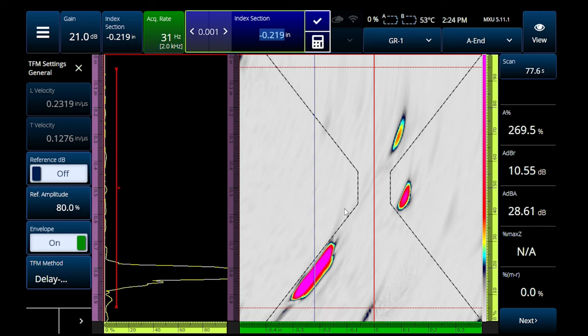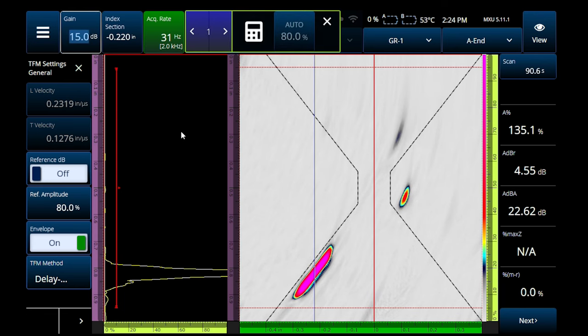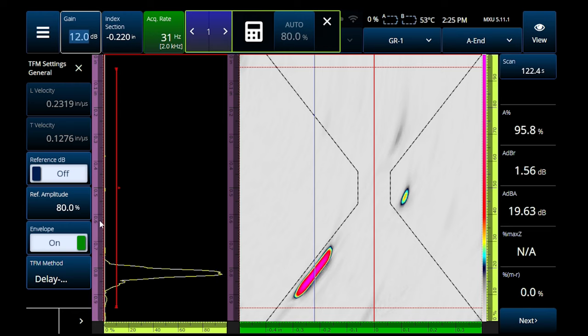If we hit it with any sort of perpendicularity, we get a nice high amplitude signal — a good specular reflection coming off the surface of this flaw — and we get a really high amplitude signal. So out of most of the welding defects that we look at, this is typically going to be the highest amplitude. If I bring the gain down, I get a very clean baseline. I don't really need PCI or TFM — this is the easiest indication to find, and bringing the gain down reduces the noise and everything else.